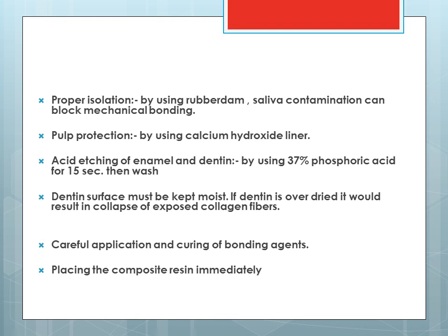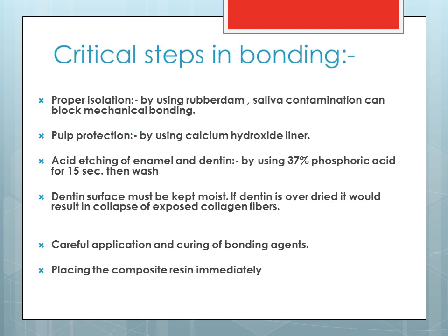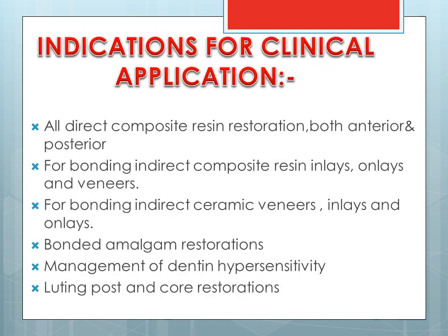Dentin surface must be kept moist. If dentin is over dried, it can result in collapse of the exposed collagen fibers. Careful application and curing of bonding agent, and placing the resin immediately. So these are all the clinical considerations which we'll be studying in detail later on. And these are also the critical steps in bonding.